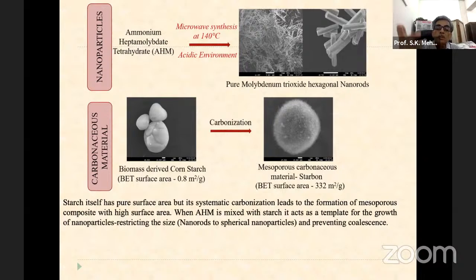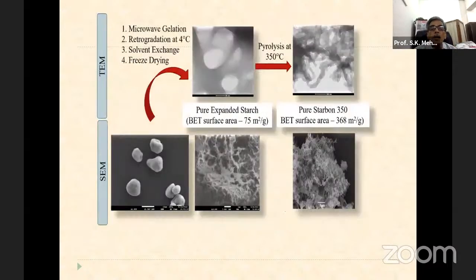So these two in combination can be easily used, and then these two are mixed with starch, and it acts as a template for growth of nanoparticles, which restricts the size also. And this is what the TEM and SEM graphs tell us. You have microwave gelation, retrogradation process, solvent exchange, freeze drying. Finally, pyrolysis can be done.